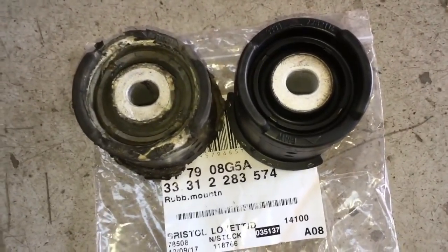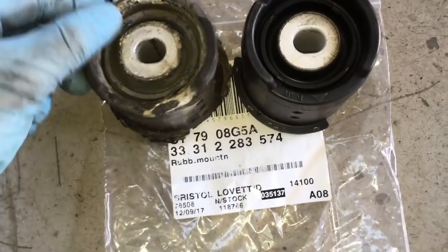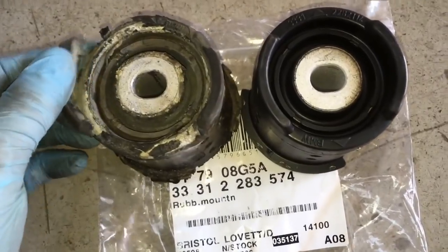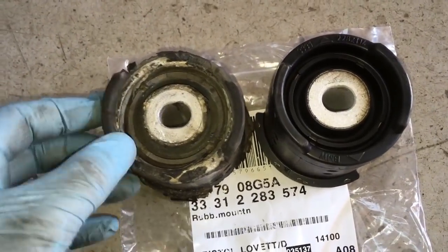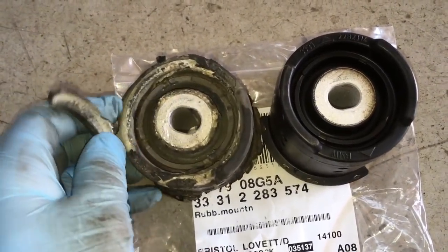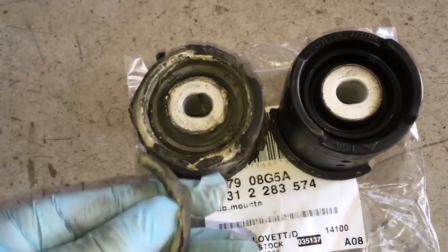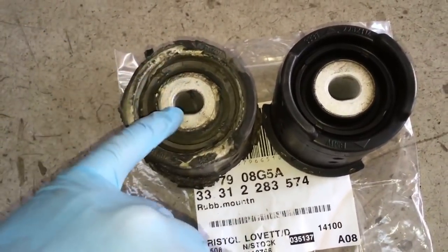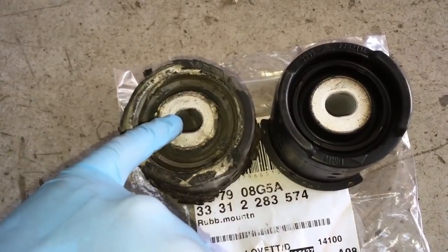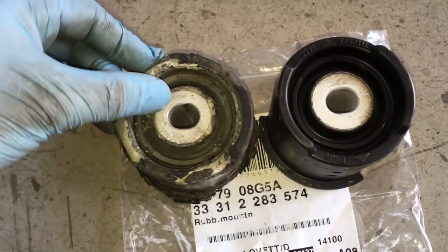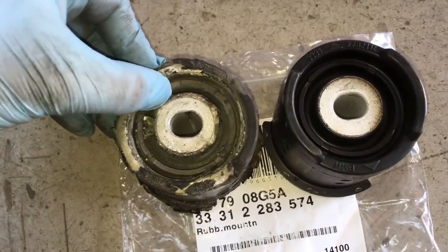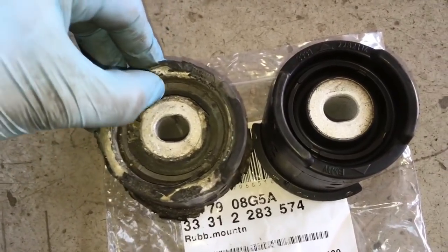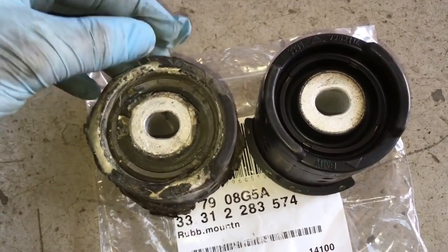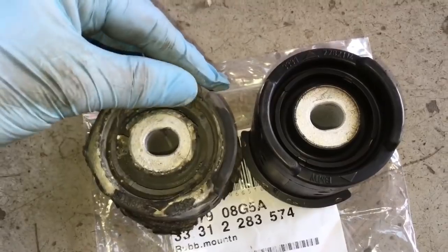Here's an example of one of the subframe bushes. There's 4 of these in total. Here's the old one that was taken out. This is the front right mount, where the actual rubber is broken apart, just crumbling, easy to pull apart. The aluminium of the shell of the outer bush and the inner sleeve is oxidized because it's bare aluminium, and that pushes the rubber, which was liquid when it was first made, away and then it just crumbles and separates.